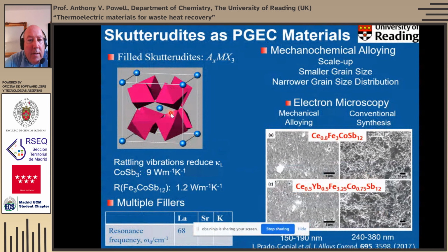If we introduce some rare earth cations into that cavity space, we have to adjust the electron count of the host as well. So we have to replace quite a lot of the cobalt with iron in order to maintain the appropriate electron count, because the rare earth is, of course, donating 3 electrons when it goes into that cavity. We can reduce that thermal conductivity by about a factor of 8 or so, and that can give rise to quite significant performance enhancements. So our interest was thinking about, well, if a single rare earth cation with localized vibrational modes can cause significant reductions in thermal conductivity, what happens if we were to use multiple fillers? Because as we can see here, different fillers have different vibrational or resonance frequencies, and therefore they're going to interfere with different parts of the phonon spectrum.